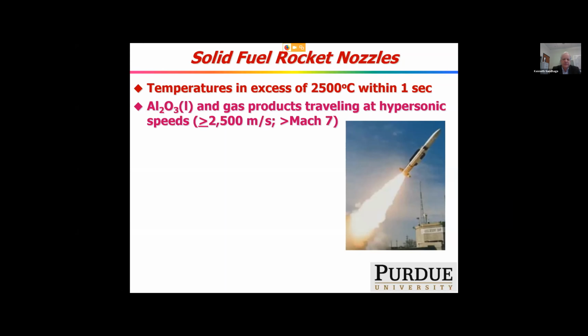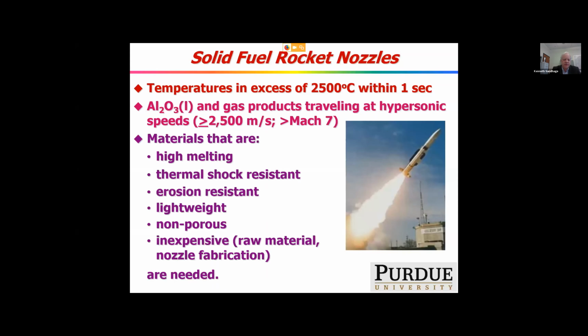So it's extremely erosive. The materials used for this you can pretty much count on your hand, because they need to be very high melting, extremely thermal shock resistant, and erosion resistant. Of course, you'd like them to be lightweight since you're launching the missile. Non-porous, meaning that you want the combustion products to go through the nozzle orifice and not through the sidewalls of the nozzle. And of course, inexpensive, in the materials you use and how you fabricate it. These are difficult combinations of properties to satisfy at the same time, and in particular, erosion resistance is challenging.